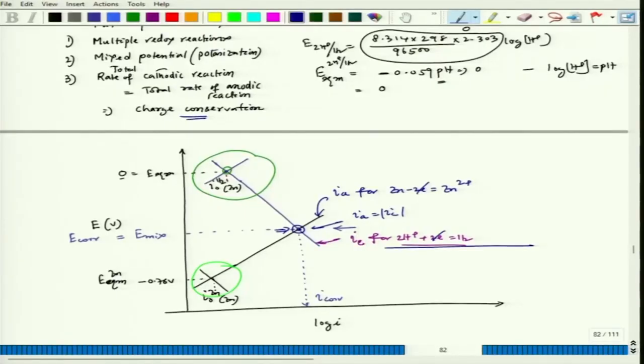Now, when you try to protect zinc, let us say I would like to protect zinc, I do not want to allow this corrosion of zinc in HCl, then how can we do it? For that, again we can make use of the principle we have discussed. So, if we go to the cathodic side, let us see. Here, again polarization we have to do. In order to reach this point, we had to see the polarization happening on the hydrogen part as well as the zinc part. The hydrogen is having cathodic polarization from its equilibrium potential and zinc is having anodic polarization from its equilibrium potential, which is minus 0.76 volt, and it is reaching in between some potential where both the current densities become equal and charge balance, or charge conservation, is maintained.